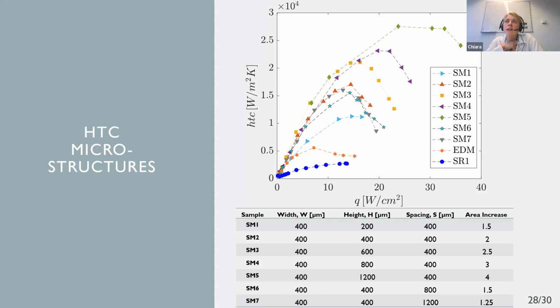Another interesting thing to notice in these results is that at heat fluxes closer to the critical heat flux, the heat transfer coefficient trend starts to decrease. And this might be related to the formation of dry-out patches, very large bubbles that start to merge, creating local spots where the vapor is in contact with the surface, and this might induce a degradation of heat transfer.